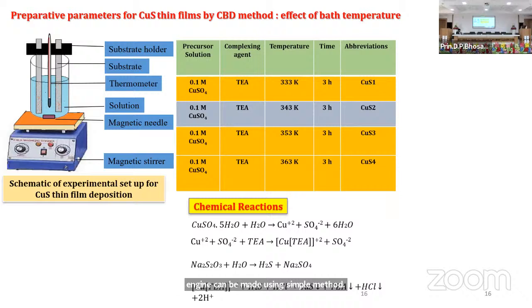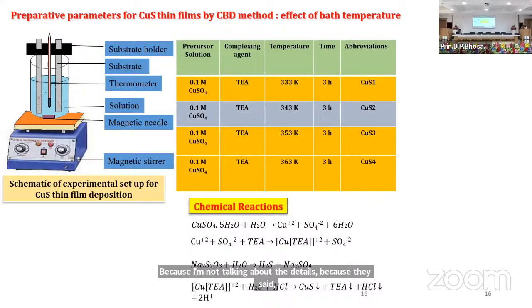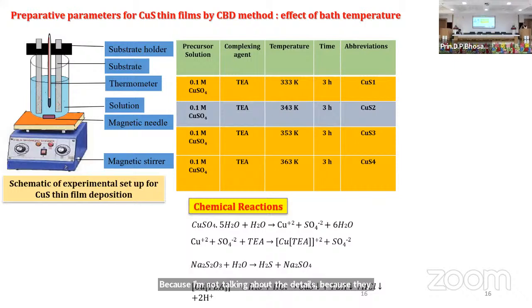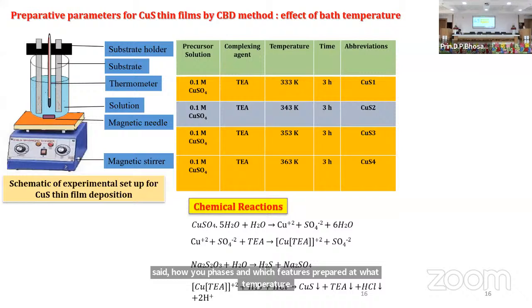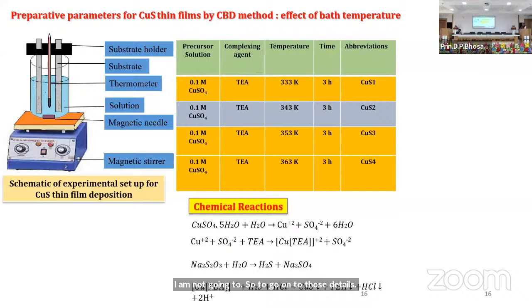So this is the copper sulfide. This also shows the supercapacitor property that we know. Of course, I'm not talking about the details because this has 5 phases and which phases prepared at what temperature. I am not going to go onto those details. But you see what we have done. We have taken 0.1 molar copper sulfate here, and we have used triethanolamine as a complex reagent.